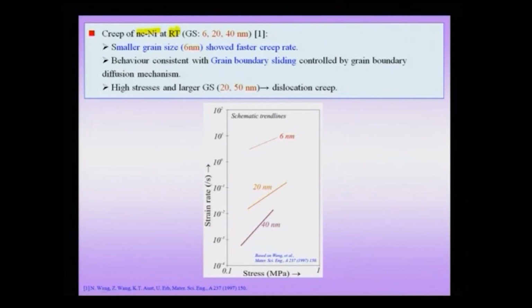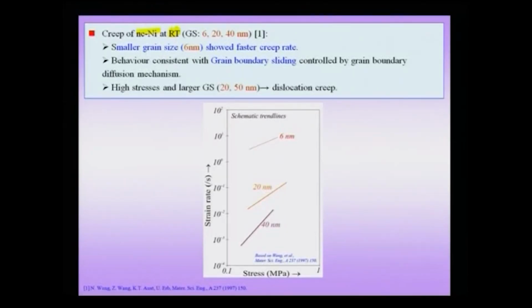So, this is very, very interesting, because this is something very close to the kind of expectation we had earlier raised, that we would have higher creep rate under two conditions, perhaps under higher strain rate and at lower temperatures. So, here the temperature is room temperature, and of course, we are now making comparisons of grain sizes in the extremely small regime, of the order of 6 nanometer, 20 nanometer and 40 nanometer. Now, if you see the plot of these three grain sizes, you have the highest grain size, the 40 nanometer grain size here, and you have a decreasing grain size as you go from here to here.